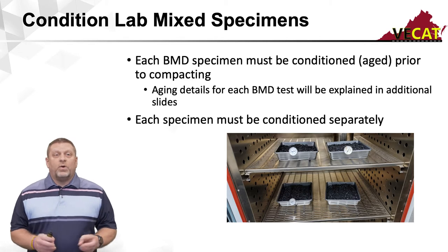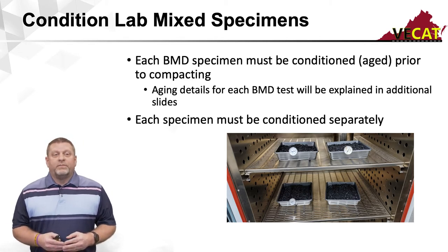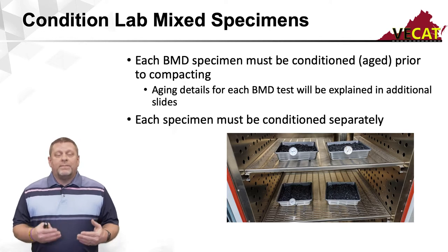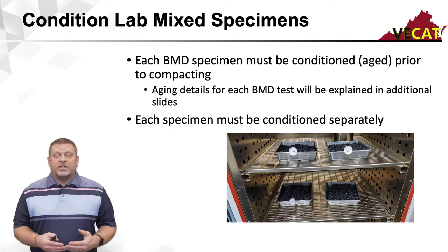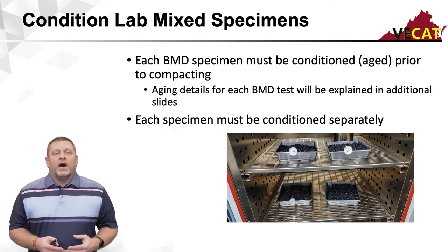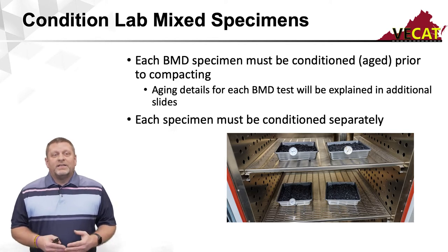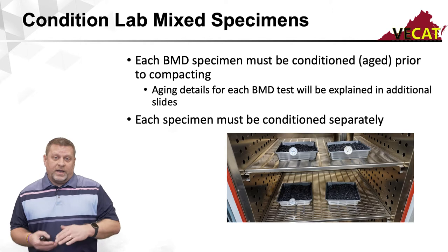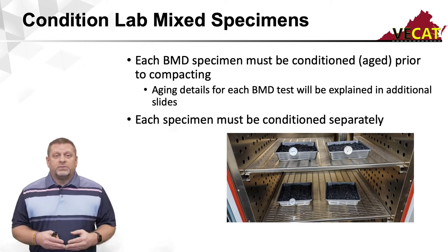It's very important when conditioning our specimens during the mix design process that they be done individually. If you elected to mix more than one specimen at a time, you have to split them down immediately following mixing, because they must have their conditioning done individually and in individual pans. Also notice in this picture that the sides of the oven are perforated — this is a horizontal flow oven, which maintains temperature much better than a direct airflow oven. It blows air in a circular format through the perforated sides, which is very important for improving accuracy.